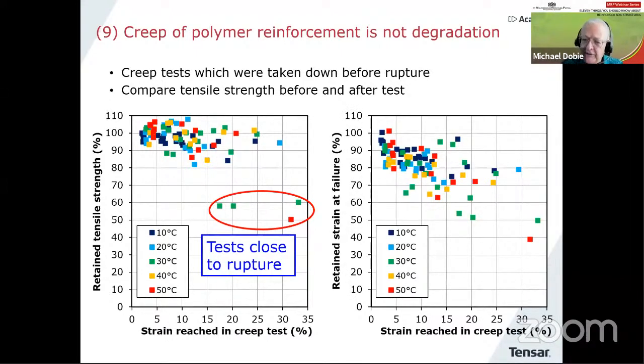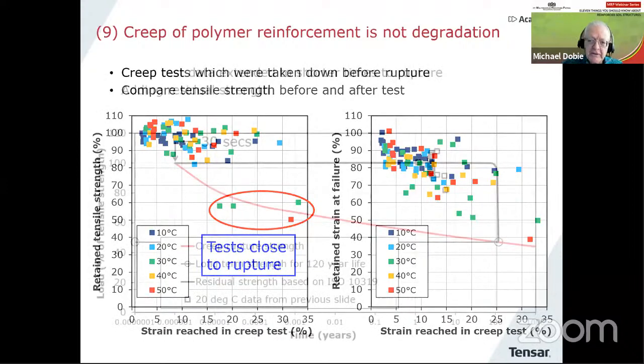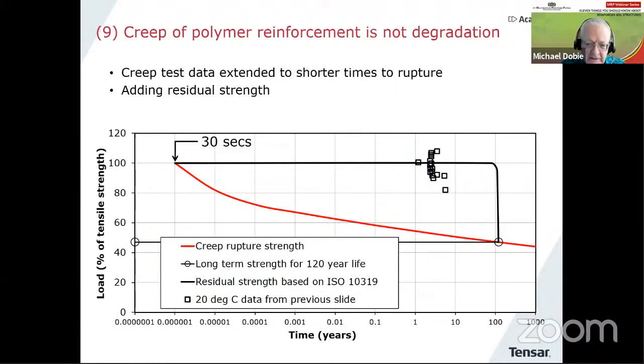So we find that the strain at failure does reduce a bit, not surprisingly, because you stretch the geogrid. So what I can do, I can add that data, there, the black symbols for the 20 centigrade data to this diagram. And you can see how it's working now. And often people will look at that and say, okay, well, in that case, why don't we design for 100% tensile strength? Well, problem was, if you do that, it fails in 30 seconds.